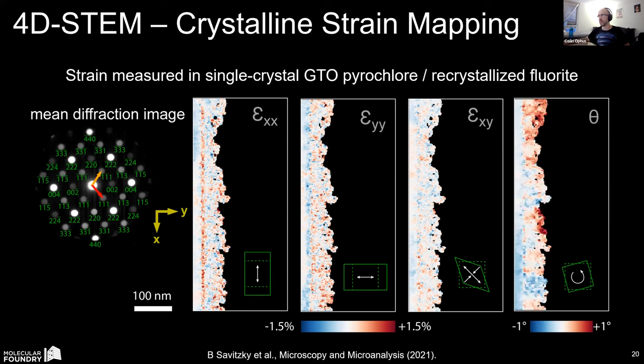And if you measure the local infinitesimal rotation, you can actually see very much on the left, no rotation of that front, and on the right-hand side, this sort of blue and red grains. And this is because when you nucleate, you often have misfit dislocations, and it will grow outwards into the amorphous phase with a couple degrees of random orientation from the parent pyrochlore structure.